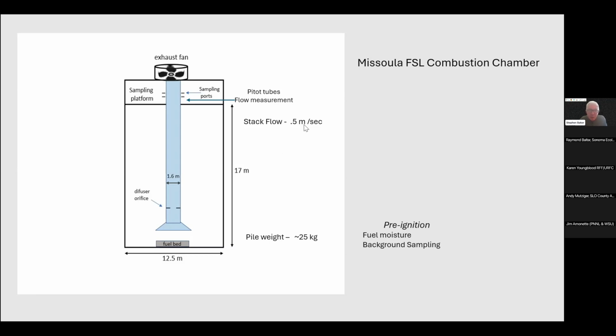With the flow that we had going up the stack, it would take about 30 seconds or a little more for the emissions to reach the platform before we actually did the sampling. And we did a background sample of canisters before each burn to get the level of especially CO2, with lots of people in there breathing and such, before we did our measurements.